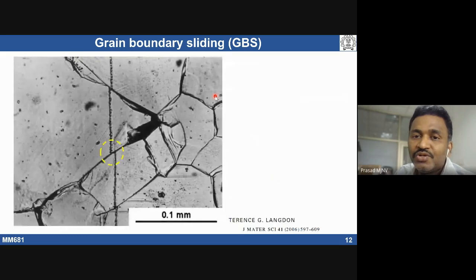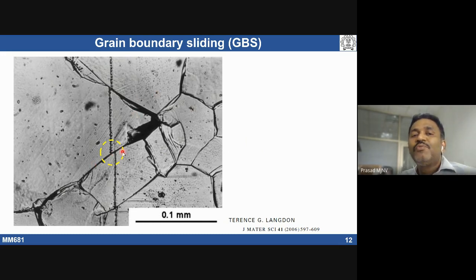If you have polycrystalline materials, what people typically do experimentally is put a micro scratch mark before deformation, and after deformation see how much width change has taken place. Calculate the average width change, and since we know the average grain size of the material, that gives the amount of grain boundary sliding that has taken place. This is the experimental way of estimating grain boundary sliding strain during plastic deformation of a material at elevated temperatures.